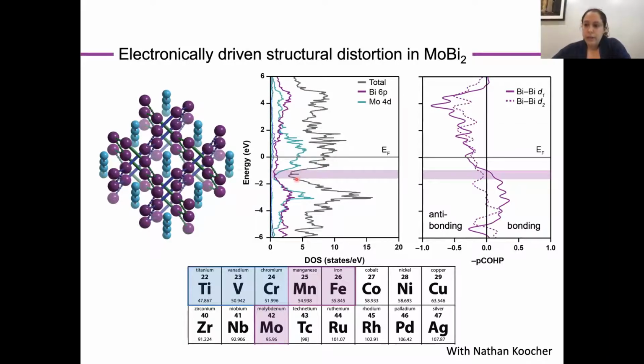And so, as you might expect, as you move to the right on the periodic table, not only do you lessen the amount of distortion, it's important to realize that you actually start to occupy antibonding states sort of across the board for all the relevant interactions in the system, including the molybdenum-bismuth interaction, as well as the molybdenum-molybdenum interaction. And so not only does that change the structure you would get, I would expect that to also influence the stability of the phases that we're accessing.